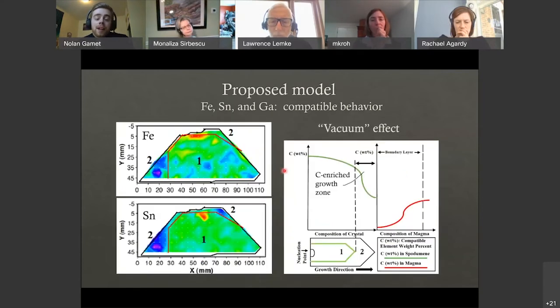Oppositely, or contrarily, iron, tin, and gallium represented a compatible behavior, as we call this the vacuum effect, in which they started off with high concentrations of compatible elements and then resulted in lower concentrations as the crystal grew.